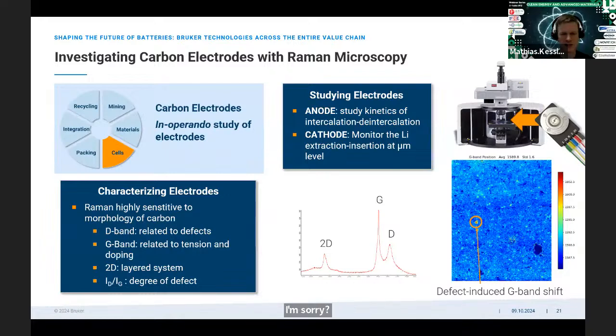We can not only use FTIR microscopy or laser microscopy, we can also use Raman microscopy. And this is, of course, also interesting for electrode studies. For example, anodes, so we can investigate the intercalation. Or on the cathode, we can see the lithium insertion or extraction. And Raman is very useful if we have carbon-based electrodes, so graphite or graphene, and there we have the prominent absorption bands in the carbon structure, and we can then nicely investigate and see defects, for example, on the electrode surface. And this is done, for example, with a Senterra or a Nanophoton Raman microscope and a corresponding Raman spectroelectrochemical cell.